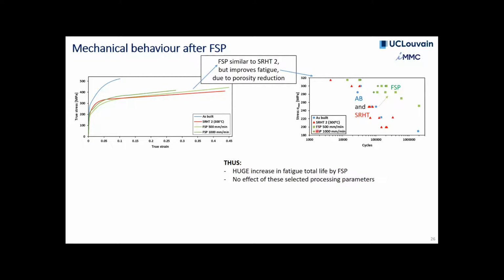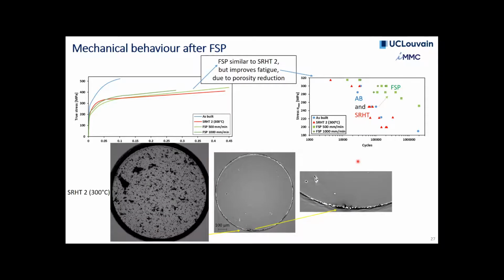If you look here, you actually have 500 millimeters per minute and 1,000 millimeters per minute parameters of friction stir processing, and basically we have the same conclusions. So really what matters is to suppress all these porosities and, of course, not get defects due to the processing conditions of friction stir processing, but that's quite evident.